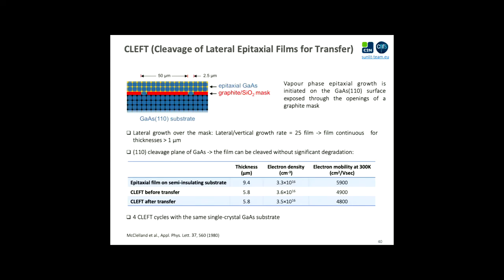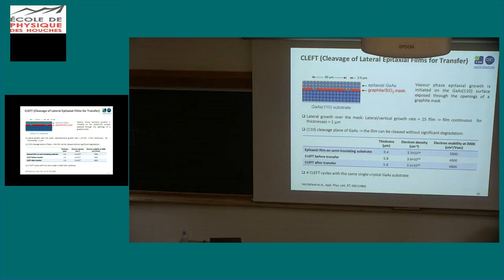There are other possibilities. I list two. So this is a very old technique, actually, from the 80s. Again, we go back to the origins. For some reason, forgotten. I really don't know why. And the idea is very simple. You get your gallium arsenide substrate, and this time you use a sort of graphite mask where you drill some holes, and then you start the epitaxial growth of gallium arsenide.